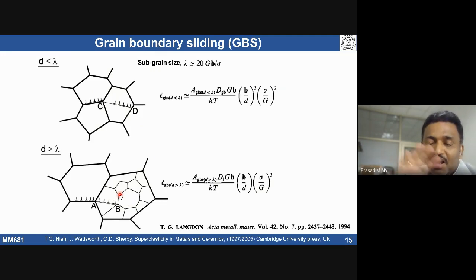Typically, in hot deformation, we do see a subgrain structure develop. During superplastic deformation, we do not see subgrain structure formation because of the fine grain size. The moment subgrains form, they are of low angle boundary character, and subgrains have a low grain boundary sliding ability. Grain boundary sliding will be more only when there is a high angle character, with a misorientation angle greater than 15 degrees. Then we can see increased grain boundary sliding activity. When you see subgrains with a low angle character, there won't be any grain boundary sliding.